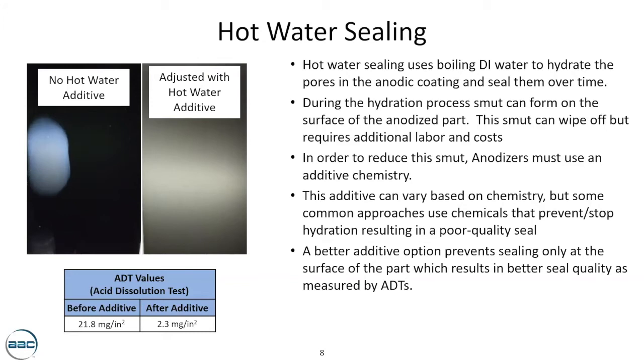So what many chemistries try to do to mitigate this is they stop hydration. Now the risk you run by stopping hydration is you're not going to hydrate the pore, and your pore, because of that, may be susceptible to poor seal quality. Certain additives only suppress hydration at the surface, which means the pore itself is fully hydrated and has its full integrity, whereas the surface where you see the smut does not. So in situations like that, when you use the correct additive, you will actually get very good seal quality, but not have the smut associated with hydration. It's almost like a targeted additive that only affects a portion of that anodic coating.